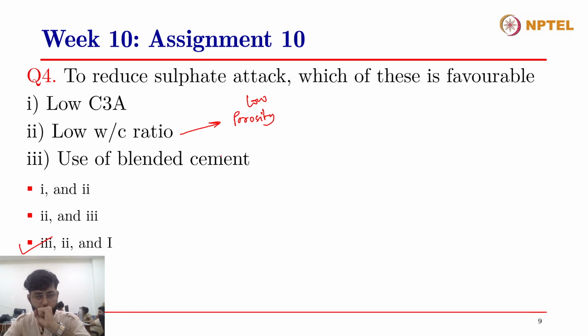When you have low water to cement ratio, you are essentially lowering the porosity in the concrete itself. For sulfate attack to occur, the sulfate ions have to get inside the concrete. When the porosity is low, the pore connectivity is low, so the sulfate ions coming from external sources like water or soil cannot get inside the concrete. There will be a barrier from the pore structure refinement itself, and due to that, the risk of sulfate attack is also reduced. So low water to cement ratio is also the right answer.